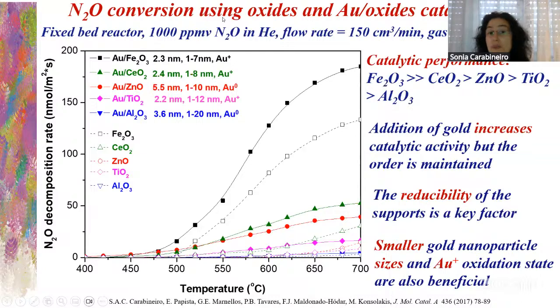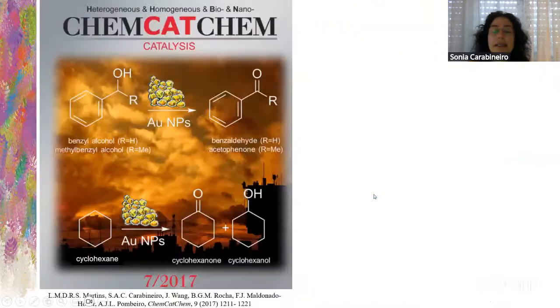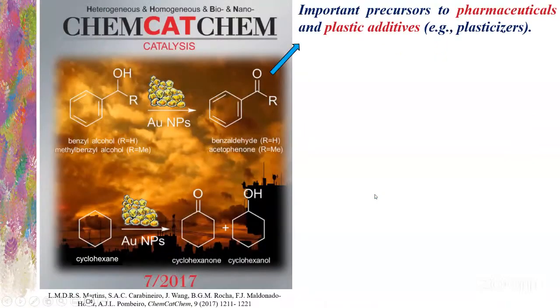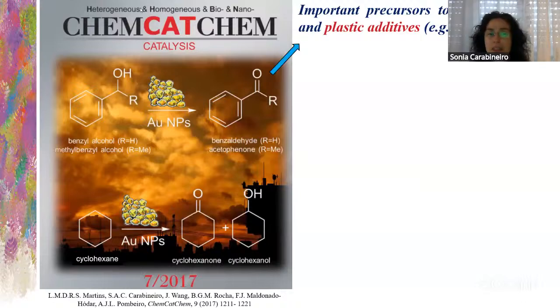But also the smaller gold nanoparticle size, and gold plus, is beneficial. We see here that those were the best samples. Here we had this cover of ChemCatChem. In these two, the gold nanoparticles were used as catalysts for oxidation of alcohols and alkanes. So we have this reaction, benzyl alcohol, used for the production of benzaldehyde and acetophenones. They are important precursors to pharmaceuticals and plastic additives.